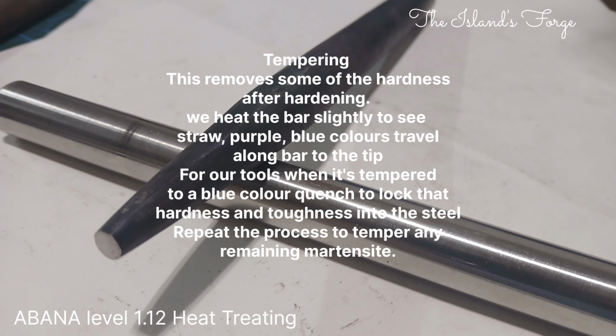Tempering. This removes some of the hardness after hardening. We heat the bar slightly to see straw, then purple and blue colours all travelling up along the bar to the tip. So for our tools, when it's tempered to a blue colour, we'll quench it, and that'll lock in the hardness and toughness to get the best tool. We'll repeat it a second time then to remove any remaining martensite that may be there.